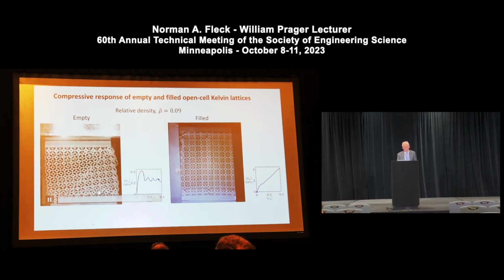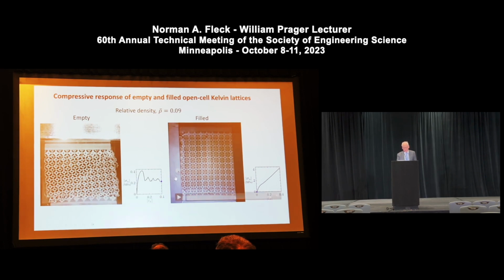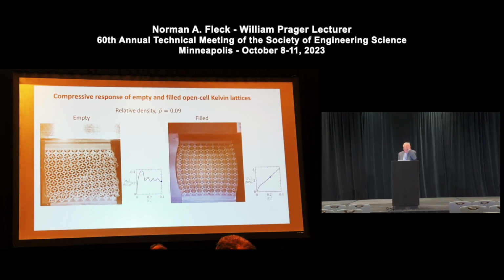Such crush bands cannot form if you were to fill the lattice, because these lose volume, and that's what we've done. So here's the filled lattice case, and you can see the remarkable stiffening that's due to the fact that the polymer, in this case the rubber, has strengthened the lattice. Now it's done so in two ways. It's done so because the mode of behavior has changed to an incompressible mode, but also the rubber as it is compressed, you could think of it as a strain hardening solid. So again, there's strengthening due to just the compression of the rubber, and that's what we wanted to separate out, those two effects.